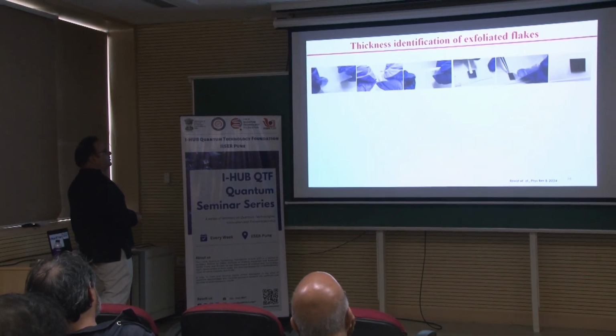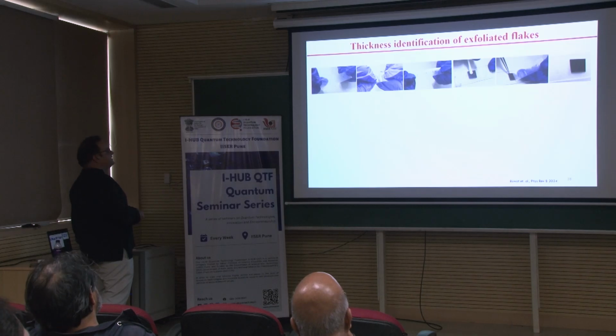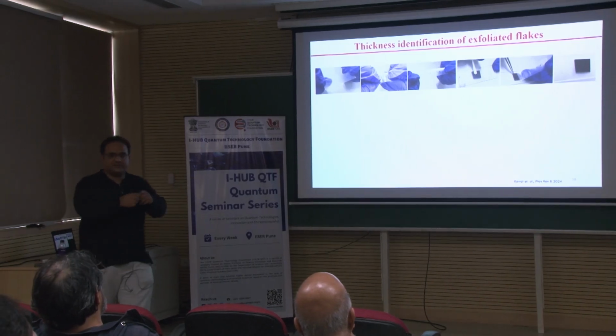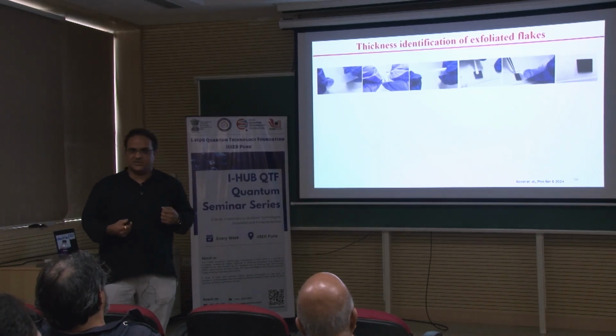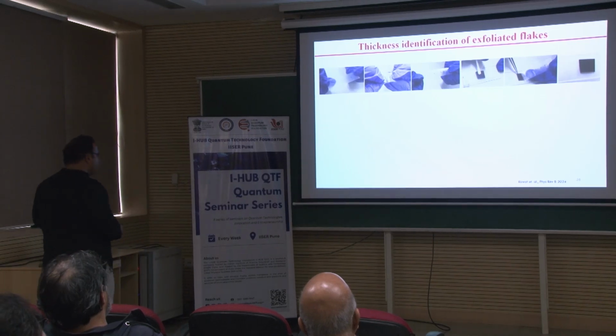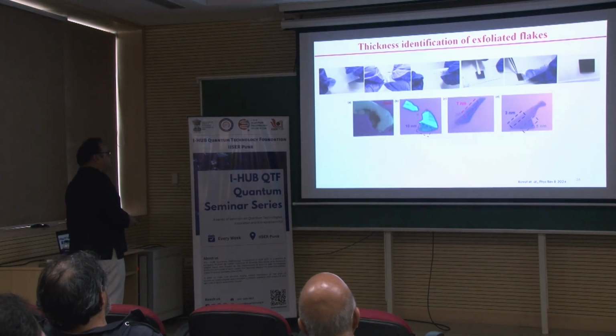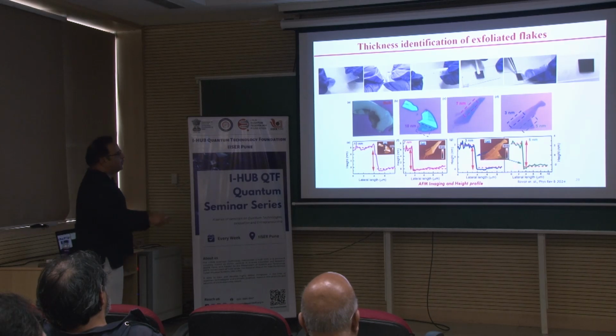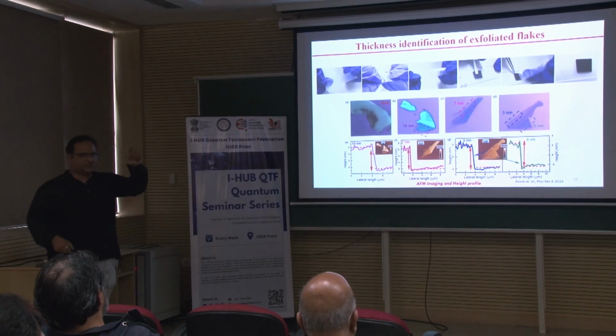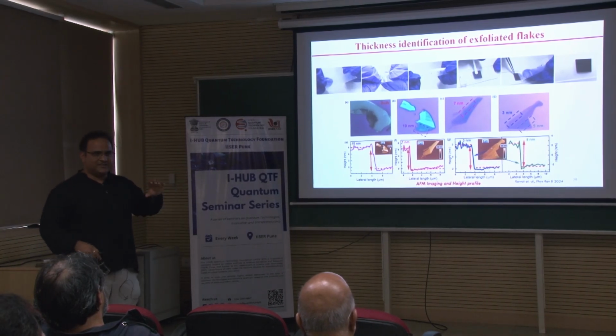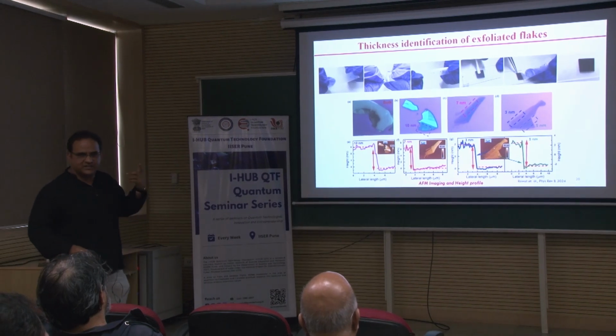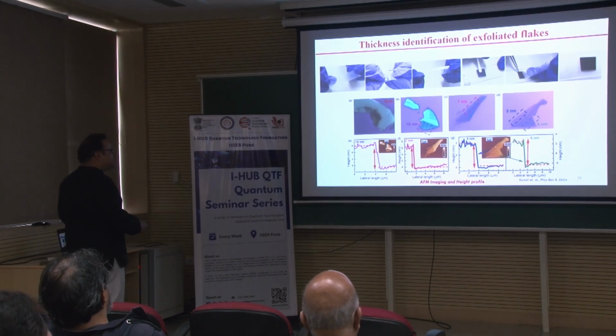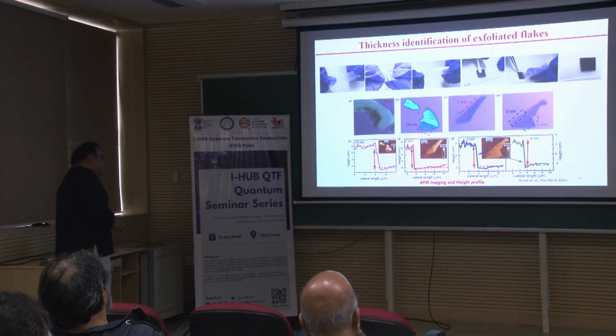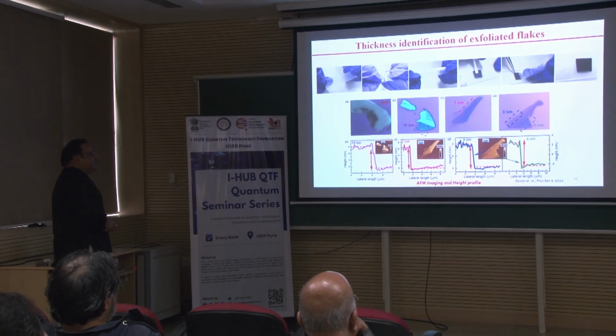So, when I am talking about dimensionality effects, what we have done is we have taken the tantalum sulphide and exfoliated it using Scotch tape, and we have moved down to a single unit cell, which is 3 nanometer. So, almost like 2 monolayers and a van der Waals gap. So, single unit cell. Going beyond that was not possible for us, and there are more reasons actually why we have not done anything in the monolayer.